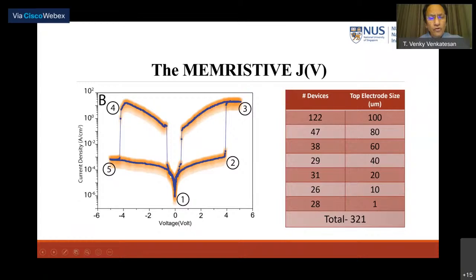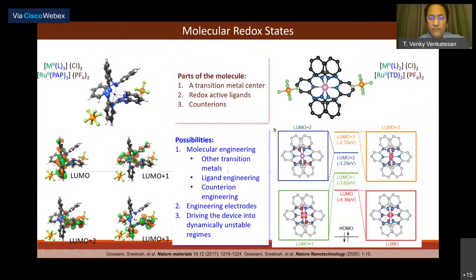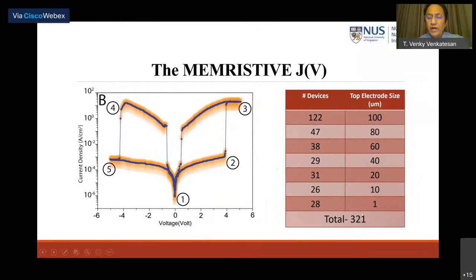Now, what is this fuzzy looking, brown cloudy thing? That is actually the overlap of data from 321 devices. These are devices ranging in size from 1 micron to 100 micron, a large number of them, and you lay all the data onto this, and this is the overlap of all these data. And for an organic system, this is truly remarkable because we have never seen this kind of reproducibility in any material system which is organic in nature. So this is one of the first major surprises for us.